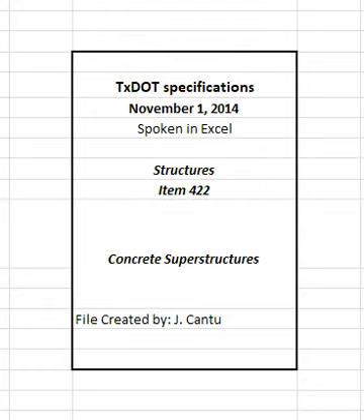4.7.1.1 Evaporation retardant. Coat the concrete surface immediately after the carpet or burlap drag, or broom finish, with a single application of evaporation retardant at a rate recommended by the manufacturer. Do not allow more than 10 minutes to elapse between the texturing at any location and application of evaporation retardant. The evaporation retardant may be applied using the same work bridge used for surface texturing. Do not work the concrete surface once the evaporation retardant has been applied.